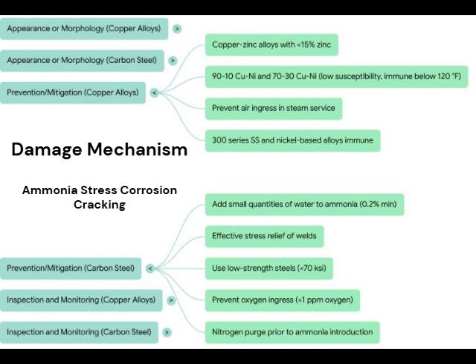Okay, prevention for carbon steel now. You can't always just swap out a massive storage tank for stainless steel. What's the approach there? For those big carbon steel structures, yeah, stress control is paramount. The number one most effective thing you can do is a proper post-weld stress relief, PWSR. Stress relief, heating it up after welding. Exactly. You carefully heat the structure, or at least the weld areas, to a specific temperature, hold it, and cool it slowly. This lets those internal residual stresses relax. It's definitely a process for big tanks, but it's vital for safety.